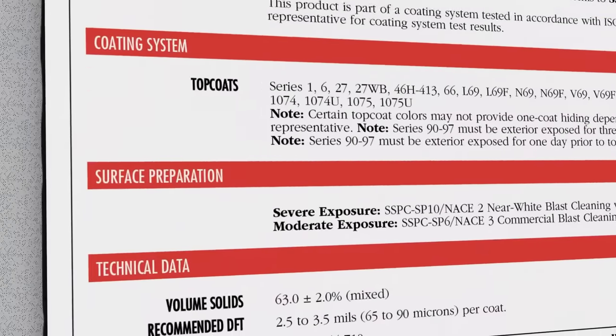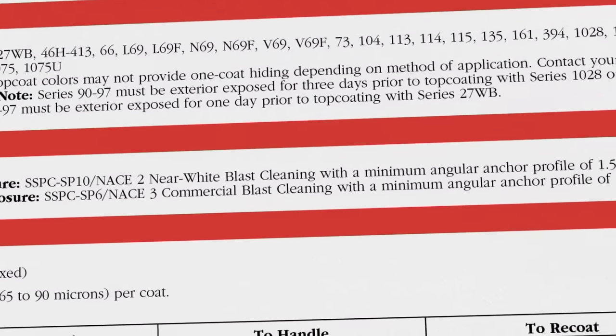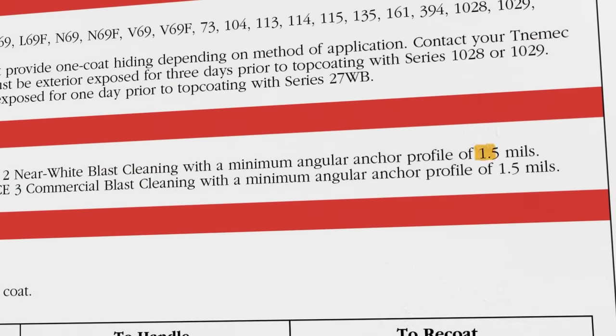In fact, let's just take a look at a random product data sheet for a high-performance primer, and you can see right there that the manufacturer recommends blast cleaning with a profile of 1.5 mils. That means the difference between the major peaks and valleys along the surface should be around 1.5 thousandths of an inch, or about 40 microns.